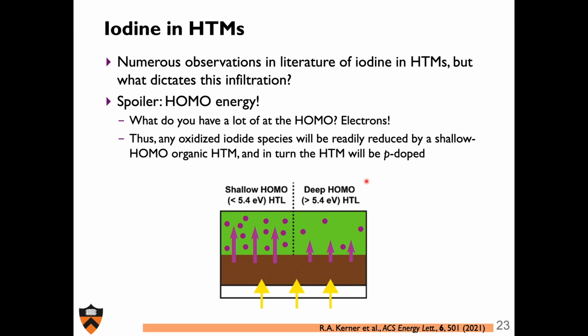So I mentioned spiro, the well-known hole transport material in perovskite solar cells. In these systems, there have been numerous observations in the literature of iodine soaking into these HTMs. But what dictates this infiltration is that when I have a shallow HOMO system like spiro, shallower than 5.4 eV, I have loads of electrons at relatively low potential, and those electrons are capable of reducing iodine and therefore getting p-doped as a result of exposure to any oxidized iodide.